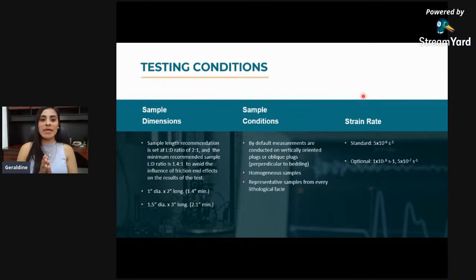Okay, now the sample conditions. For the compressive strength test, you normally want vertical plugs. What this means is that when you have your core, you identify the bedding, and normally you do the plugging or sampling in a vertical way, or you identify the orientation of the bedding and you want a plug that is oriented perpendicular to the bedding. Then again, homogeneous samples and representative samples from every lithological facies identified in your core.